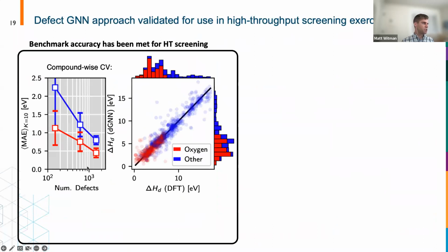So we validated this approach. Our data set, as I mentioned, is up to about 1,500 unique symmetry sites across 200 crystal structures. So that's a pretty small data set for deep learning. So here we're just showing the decrease in error as a function of the buildup of the training set. So we're still in this data limited regime where the model accuracy is still going to improve quite significantly as we add more data. And that's, of course, what we're working on in future steps. But here you can see that the oxygen mean absolute error is below this 0.5 eV, which is kind of like our target for being able to do successful materials discovery.